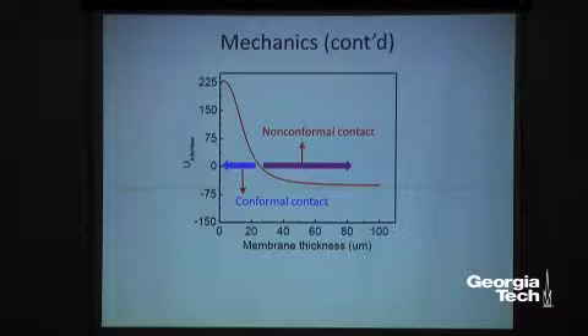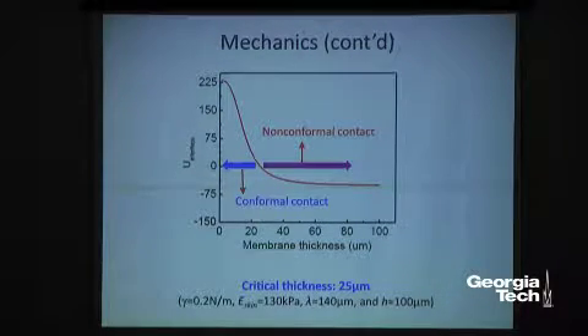Then by solving this equation, you got this nice plot showing the relationship between interface energy and the membrane thickness. So as you can see, we start from 100 micrometers, right? We reduce the thickness from 100 to 1 micrometers. Now you see that the value was negative, but after 20-something micrometers, it becomes positive. So now your bending and skin elastic energy becomes negligible so that you can get this nice conformal contact. So based on average values of your skin parameters, it's not applicable for everybody, but we use average values of skin parameters to calculate this critical thickness of membrane for having conformal contact, which was about 25 micrometers.